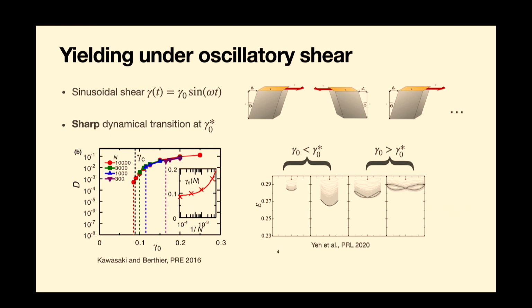So if you look at stroboscopically recorded configuration, so you always go back to the same point of the period, you look at the system and then you compare from period to period, what you see is that above a certain amplitude there is diffusive motion, so there's a non-zero diffusion constant, whereas below a certain amplitude, essentially there's no motion that you can record. So it looks like the diffusion constant there drops to zero, and you have a dynamical transition, not unlike a sort of glass transition at that point.